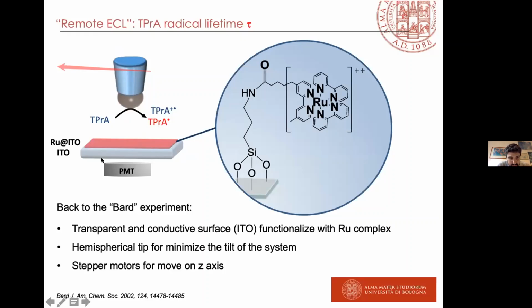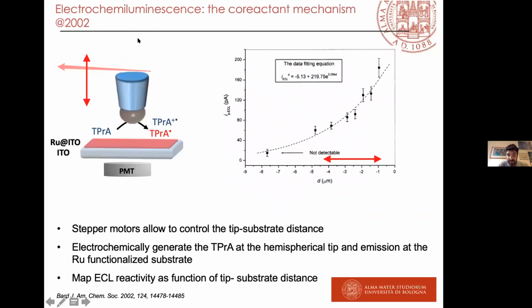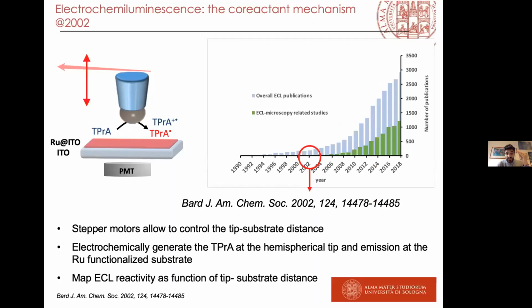Dr. Bard, in 2002, put a photomultiplier tube under the ITO electrode. So by moving towards the bulk of the solution or close to the ruthenium layer, we can obtain a map of the emission. And if you move distant from this electrode, you measure this decay of the ECL intensity. This decay is strongly connected with the travel distance of the TPrA radical and radical cation. So by moving up or down, it can measure this travel distance. And this was really a revolution, let's say, in the field.